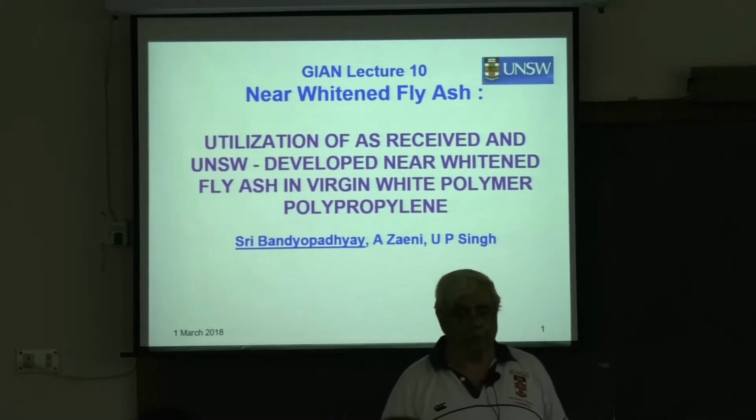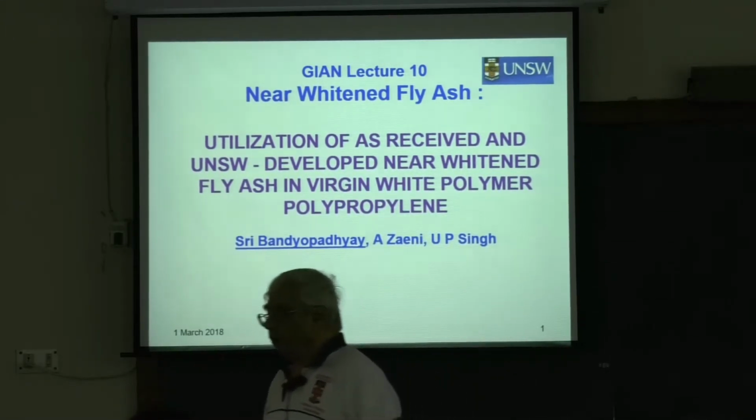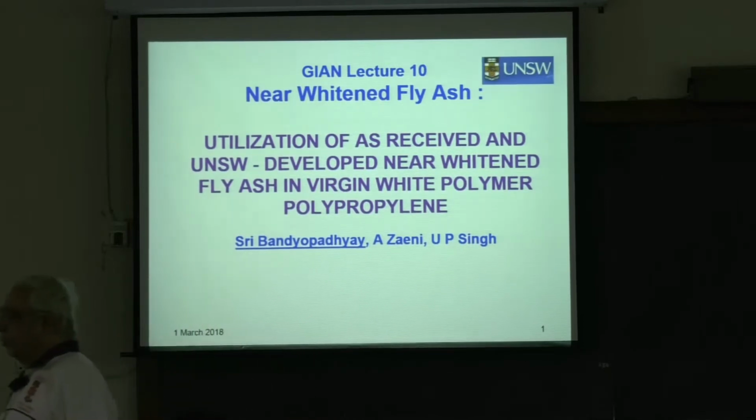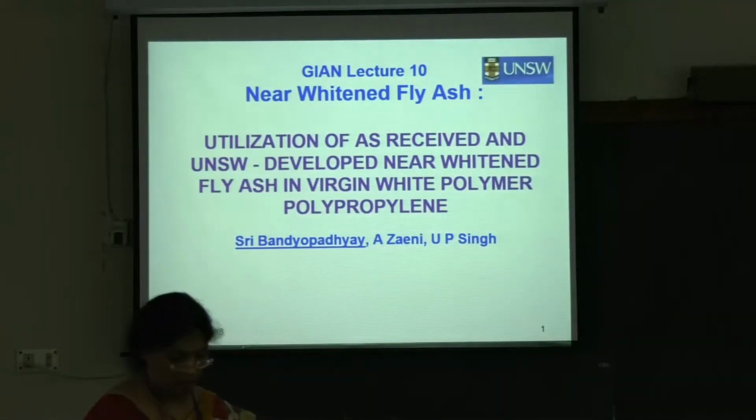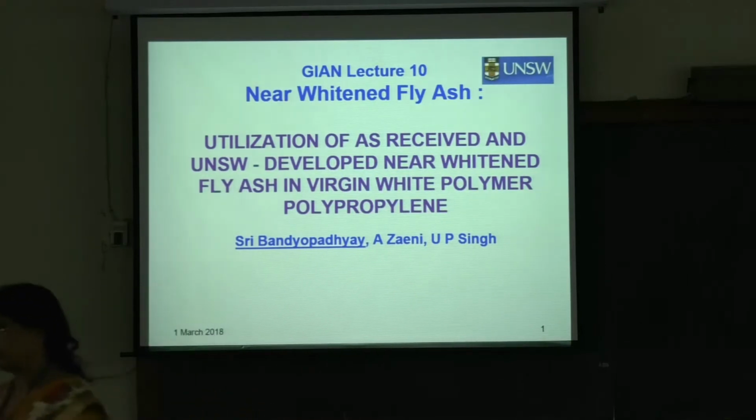If the fly ash is heated in a furnace, the carbon can disappear, and it can make the fly ash more white. So, normal fly ash can be used in many applications, but there are times when you have a white product, it reflects more light.